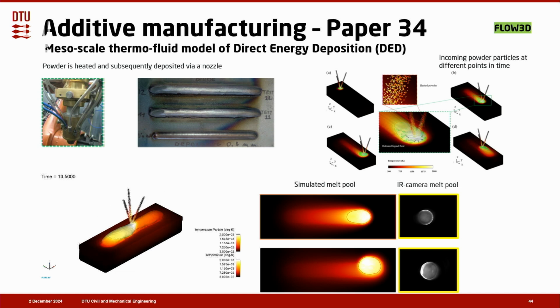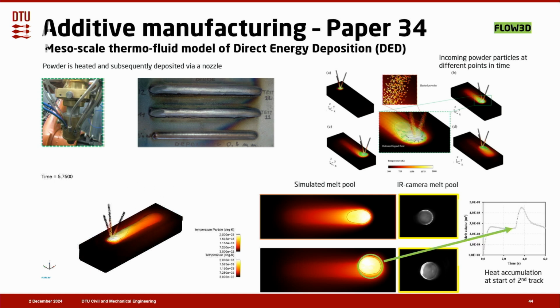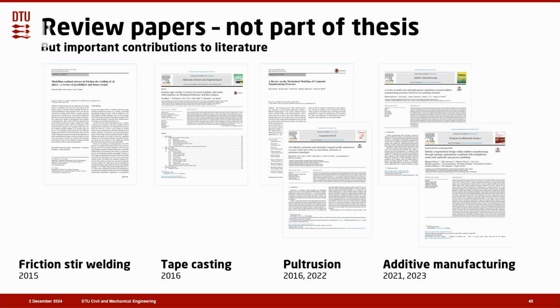And you see here at the bottom, you actually have made one scan, and then you're turning around and going back. So you, of course, get heat accumulation here at the start of the second track. That, of course, makes sense because you scan on something which is already warm. And this is what we could predict here. So these were the 34 papers, and I can see that at least some of you are still awake.